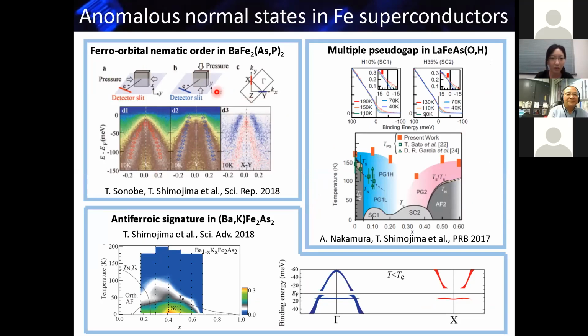But we've been also working on these iron-based superconductors. So maybe you already heard in some lecture, but in iron-based superconductors, there are many new quantum states appearing. For example, there's a ferro-orbital nematic order appearing as this different energy between these dxz and dyz orbitals. And also we get many kinds of unusual phase diagrams, like multiple superconducting gaps and some hidden electronic structures appearing in this anomalous normal state. So I won't go into detail, but ARPES can measure this kind of superconducting state and anomalous normal state and these electronic bands in these many strongly correlated systems. So okay, and